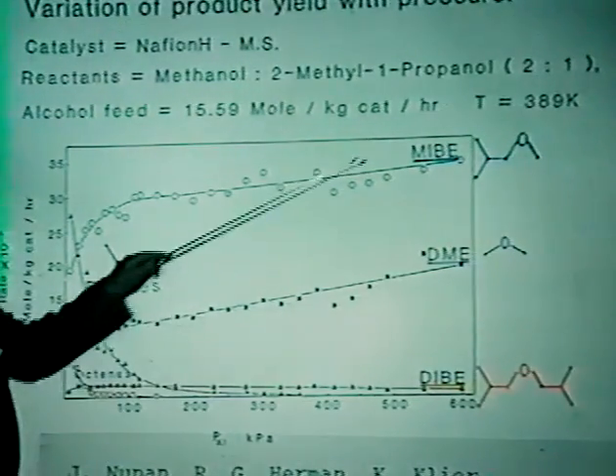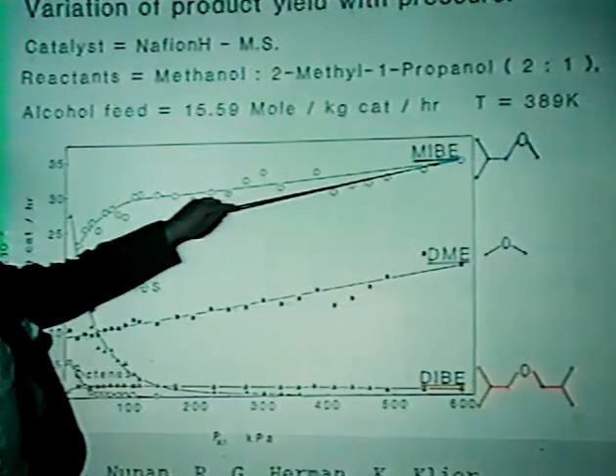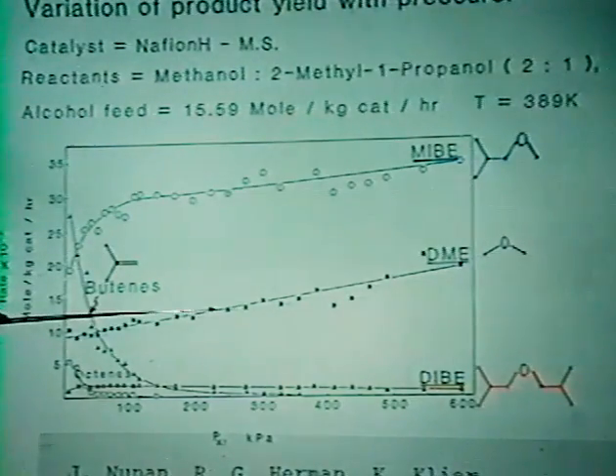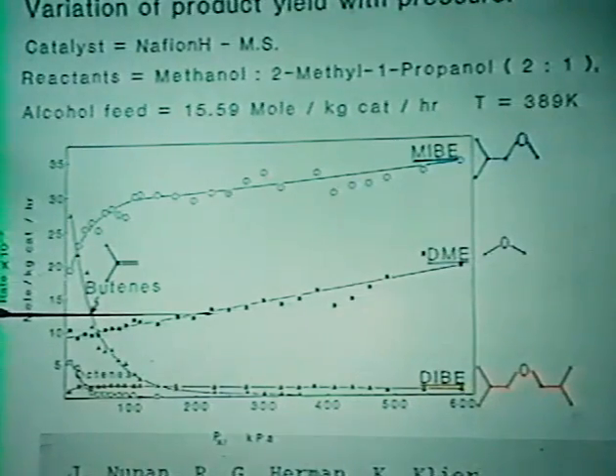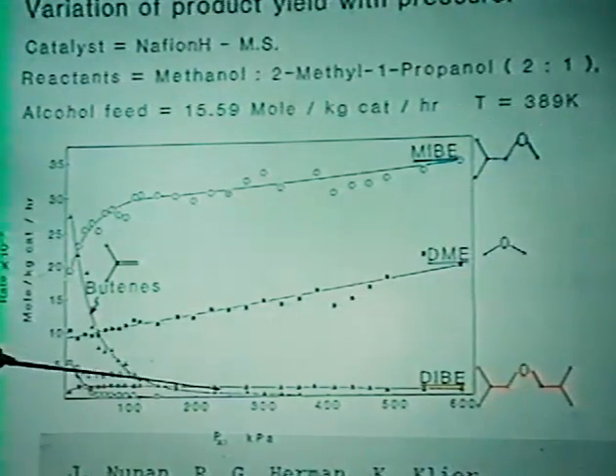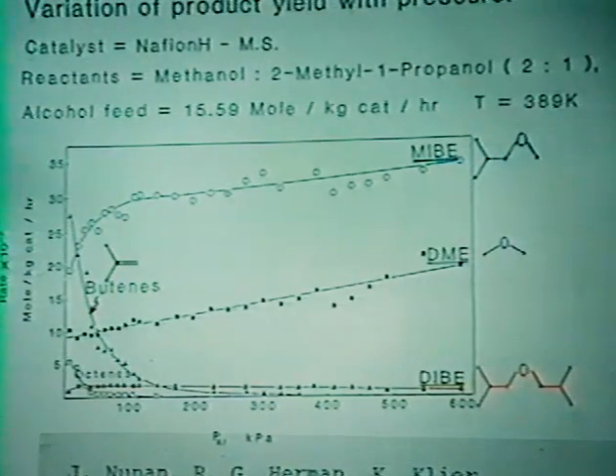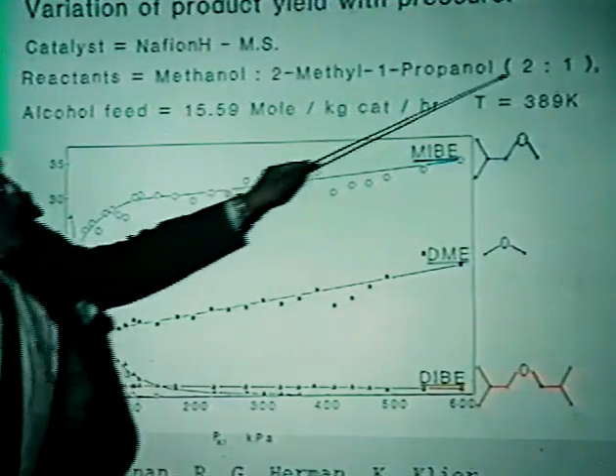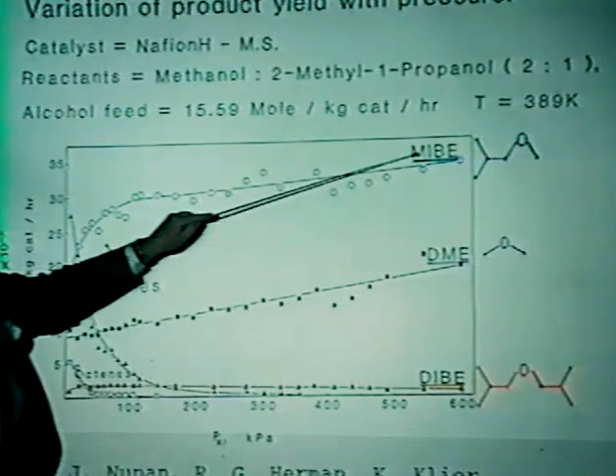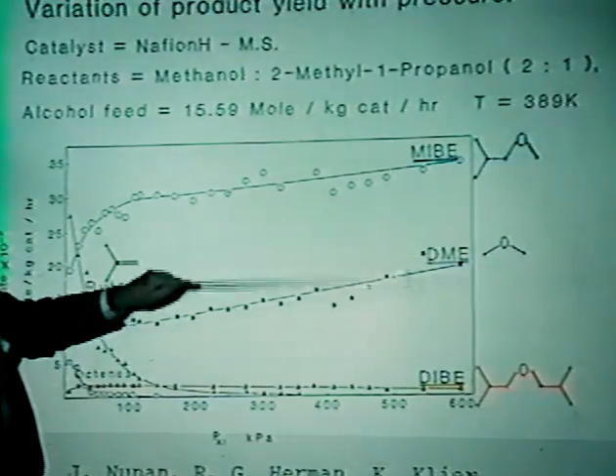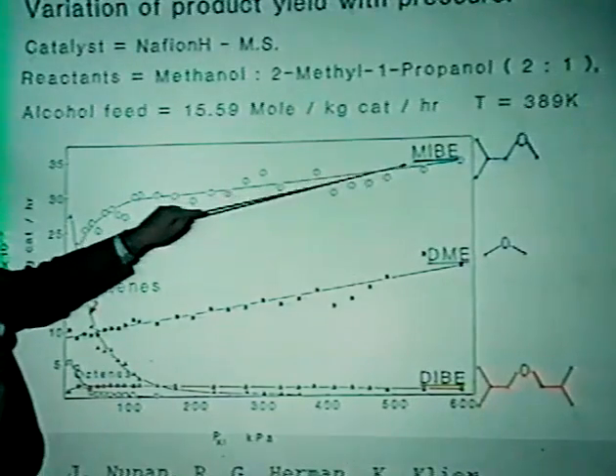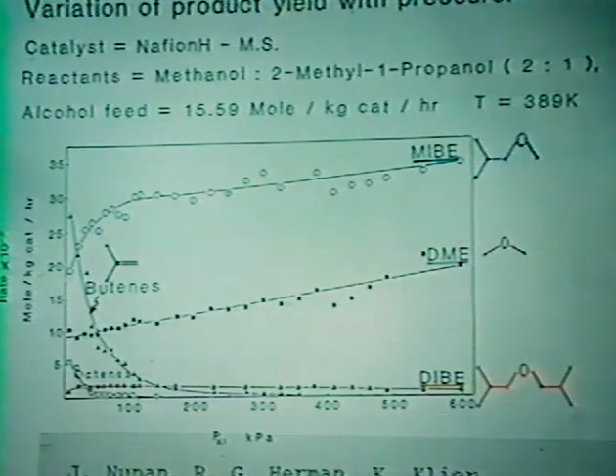And furthermore, what causes the selectivity to MIBE to be so much larger than that to dimethyl ether or even to diisobutyl ether? If statistics were true, in other words, if it didn't matter to the catalyst whether it combines methanol and isobutanol, isobutanol and isobutanol, or methanol with methanol, then these ratios should be, with this input ratio, 4 to 4 to 1. But they are something like 19 to 9 to 1. So we have an extraordinary selectivity to the mixed ether.